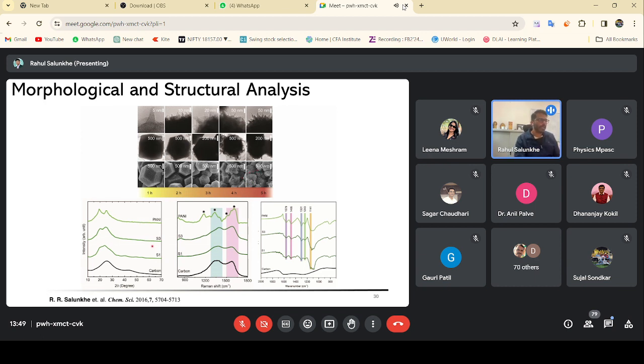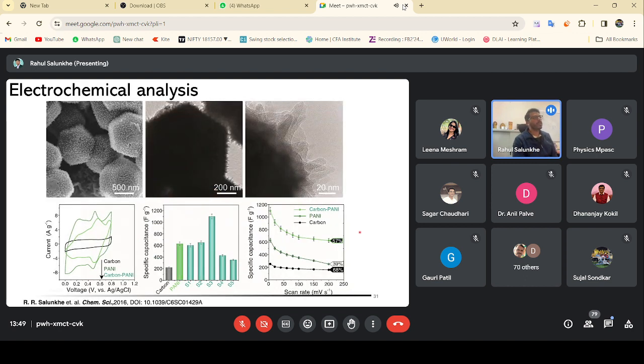Various characterization techniques like XRD, Raman spectroscopy, and FTIR analysis were carried out to confirm the coating of polyaniline on the surface of the material and the thickness variation. And we observed that for the 3 hour sample, a very uniform coating can be observed, and these polyaniline nanorods can be seen on the surface of the material.